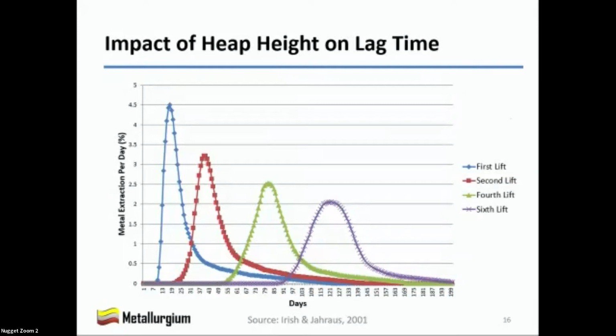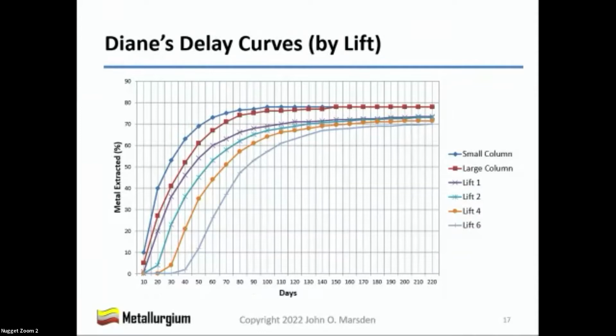And of course, for many years, we've known that as you add a lift onto a multi-lift leach pad, the grade of solution coming off drops because you've got dilution in the ore underneath. And of course, you've got delays just due to physical transfer of solution through the heap. Next slide. So Diane prepared another set of curves showing what she would expect to get out of each lift of the leach pad in terms of the timing.